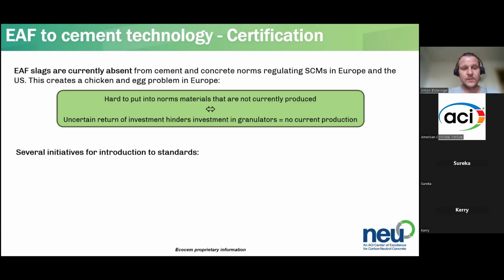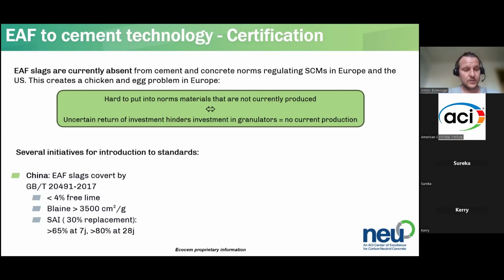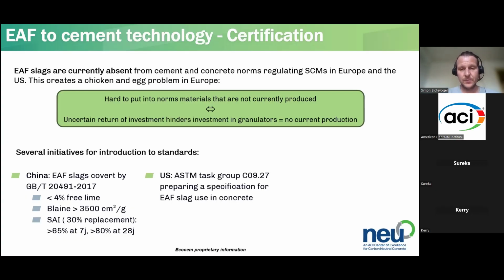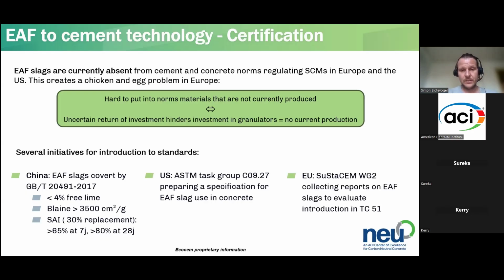If you look outside Europe, there are several initiatives, and actually I learned not long ago that China has already covered the EAF slag use by an existing norm with parameters that are quite logical. They limit free lime, they limit Blaine surface, and they have a strength activity index criterion. The ASTM has also a task group, C09.27, that is preparing a specification for EAF slag use in concrete with rather similar ideas than China has. And in the European Union, there's the SuStaCEM project where working group 2 collects reports on EAF slags to study their introduction into the cement norm that is led by TC51.